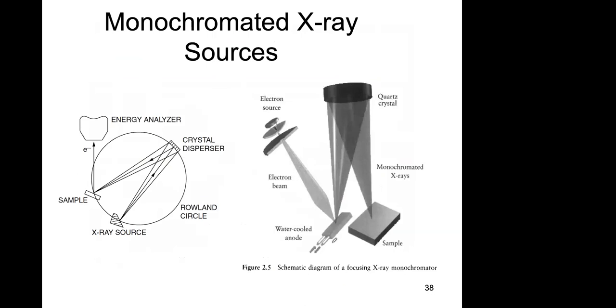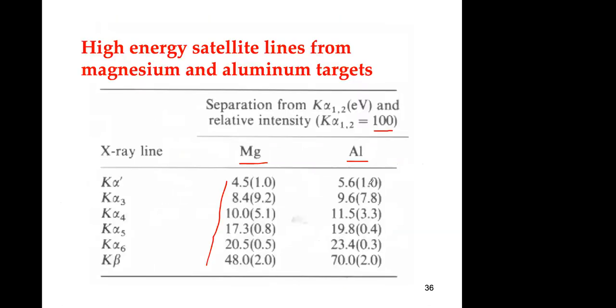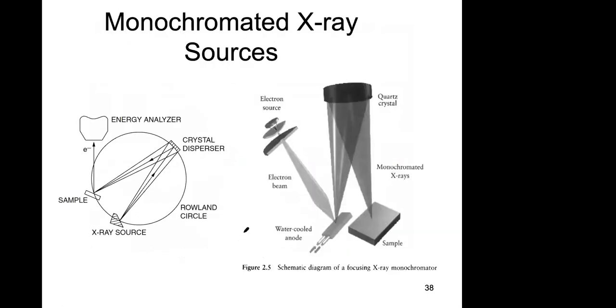So to improve the resolution or to eliminate, for example, these satellite peaks that might come up from these other photons, and to just select the right energy, you can include what is called a crystal analyzer. So you have your X-ray source, and using Bragg's law that you saw last week with Professor Brock, you will select one energy, and that energy is the one that is going to hit the sample. So here you have probably different lambdas, no? Very narrow, but you will have different lambdas, and probably one lambda hitting the sample. So you improve in that aspect. The only drawback is that the intensity of photons will be lower, because the photons are filtered with the crystal analyzer.